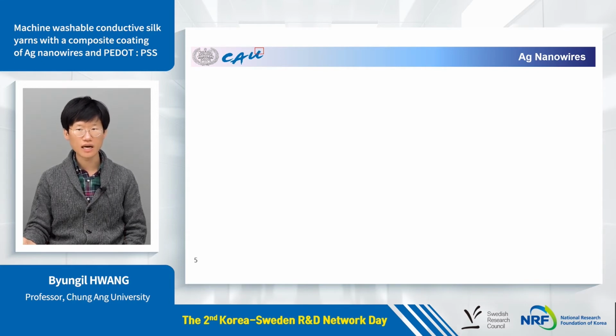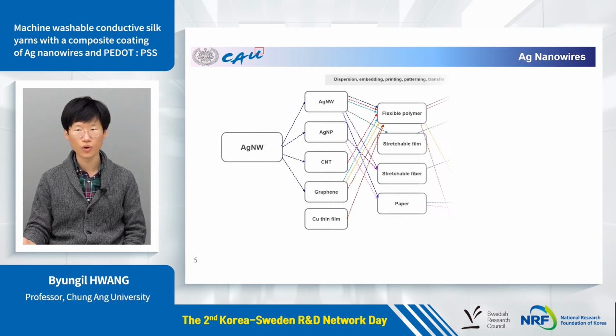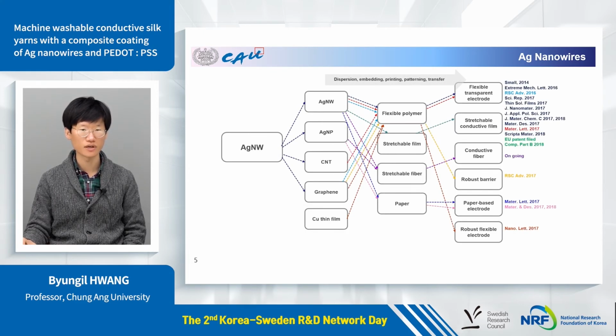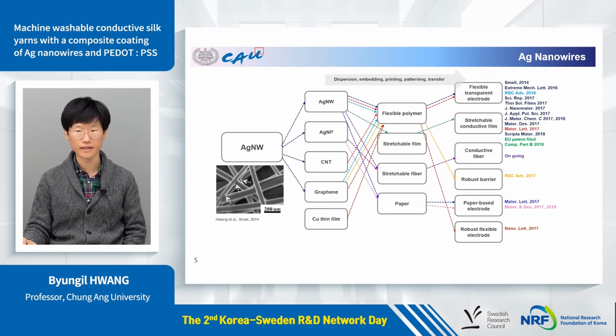At the time, I was intensively working on silver nanowires and publishing quite many papers about silver nanowire-based electrodes. Silver nanowire is a hair-like structure of silver at the nanoscale, and the wires can form a network structure, thereby providing high mechanical flexibility as well as excellent conductivity. Also, they can be easily coated on various surfaces with a simple coating process.